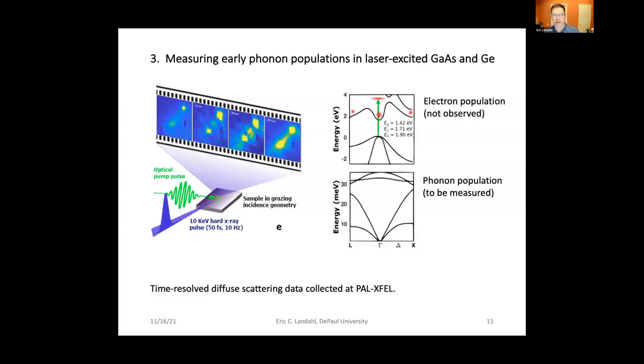And so this was sort of a holy grail experiment which we'd wanted to do 20 years ago, but really was impossible until the advent of X-ray free electron lasers. So here's some new results where we actually try to see where it is that the electrons produce phonons in a measurable way throughout the Brillouin zone. This is now becoming a fairly standard diffuse scattering geometry. You work at grazing incidence, so the X-ray and laser beams match in penetration depth, and you take frames showing at different time delays what the scattering looks like across the Brillouin zone.